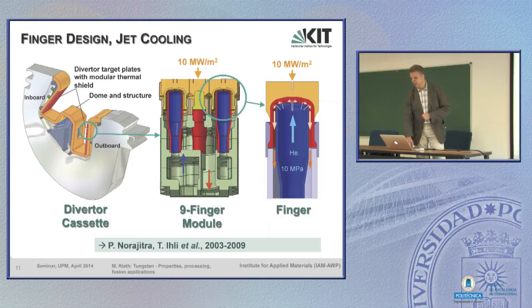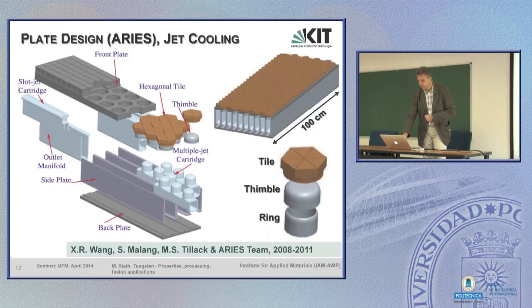We have a very high heat load, about 10 megawatts per square meter. That's an immense heat load. And if you assemble a few 100,000 of such fingers together, you can fill an area, a cooling area on such divertor cassettes, which are arranged circularly inside the reactor. And so there are two typical applications. This one for armor, for protection, and another one as a structural material.